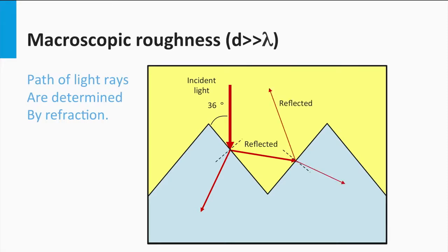Here, part of the light will be transmitted into the layer and effectively less light will be reflected in reference to a flat interface. Summarized, we have discussed 3 types of anti-reflection approaches: a Rayleigh film, anti-reflection coating based on destructive interference, and hence incoupling of light due to scattering at textured interfaces.